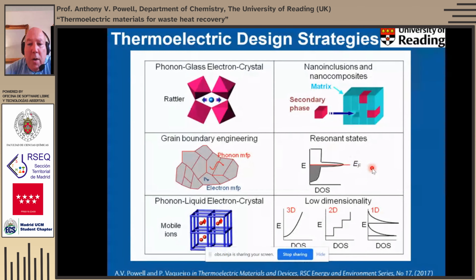Resonance states is again one I won't speak about. This is really trying to tune and adjust the band structure itself by introducing fairly deep-lying impurity states to introduce a perturbation into the band structure. So for instance, thallium in lead telluride is a prime example where resonance states give rise to a high thermoelectric performance.